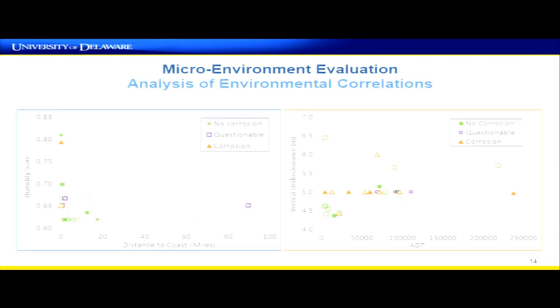So the results of those visual assessments were used to classify all of the bridges we looked at into two categories: there was active corrosion or there was not active corrosion. And then based on that, we plotted those bridges as a function of different parameters. So for example, for the bridges along the Gulf Coast, we have humidity on one axis and distance to the coast on the other axis. There are two bridges in the Gulf Coast that we classified as having active corrosion, and what they have in common is they both have a very small distance to the coast. It's less than 1/10 of a mile.